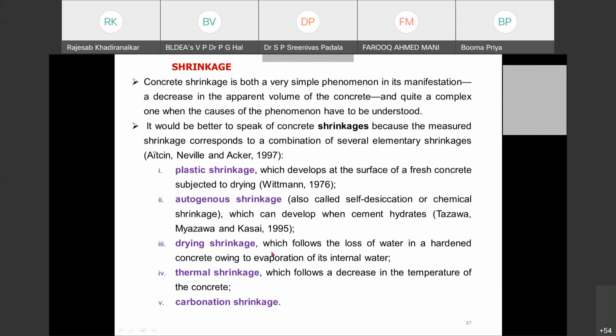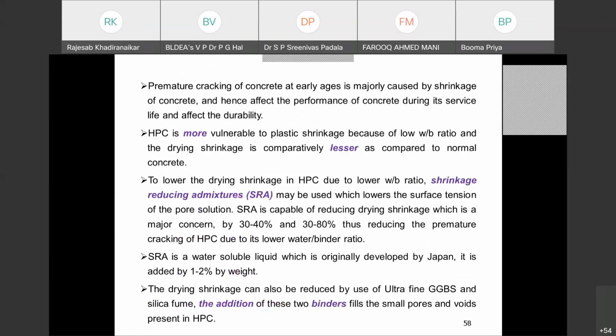And here it is less because we have less internal water in the case of high performance concrete. Then thermal shrinkage follows a decrease in the temperature of concrete, and there is carbonation shrinkage. This depends on the permeability of cover concrete as well as the thickness of the cover concrete. Since your cover concrete here is very dense, this is also reduced. So all these things contribute to the total shrinkage. The premature cracking of concrete at early ages is due to shrinkage, and this in turn affects the performance as well as the durability. So in HPC, of course, total shrinkage is less, but it is vulnerable to plastic shrinkage, because with a lower water cement ratio the rate of loss of moisture from the surface is much higher compared to the rate of bleeding. So normally it is more vulnerable to shrinkage.